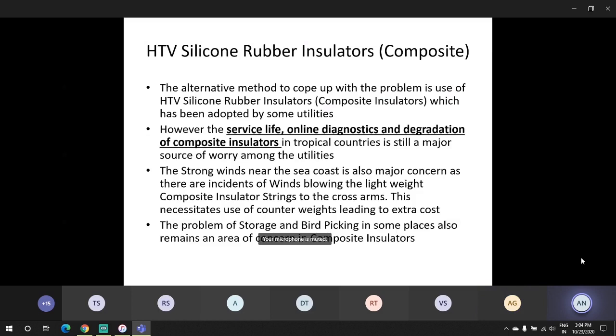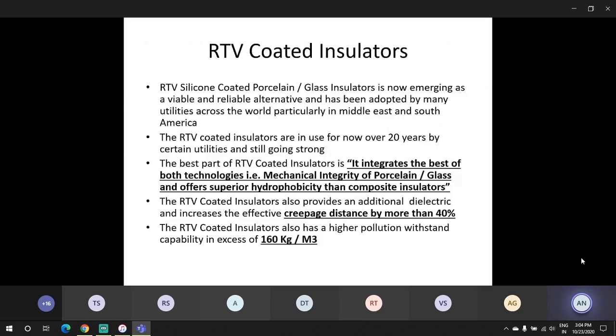There are some drawbacks in all the technologies, particularly in porcelain because of wettability, and in silicon rubber insulators due to lightweight, diagnosis, and some problems of storage and bird pecking in some areas. To overcome that, we have come out with the technology of RTV coated insulators, which can be coated on porcelain and glass as a viable alternative. This technology has been in use for more than 20 years by many utilities across the world. The best part of RTV coating is that it integrates the best of both technologies: the mechanical integrity of porcelain and superior hydrophobicity compared to composite insulators. It also provides an additional dielectric and increases the effective creepage by more than 40%. RTV coated insulators have a higher pollution withstand capability in excess of 160 kg per meter cube.